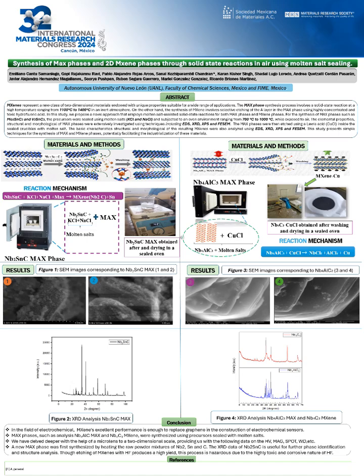Nb2SnC MAX is obtained after this process, and we proceed to dry it in a sealed oven. By doing this, we can identify in the SEM images corresponding to the Nb2SnC MAX that the layers are forming. Even though it is not a perfect formation, we can see the effectiveness of the new process without the harm of using hydrofluoric acid. Also, the XRD analysis is located at the end of the left side of the poster.